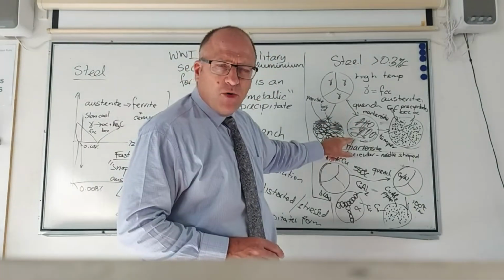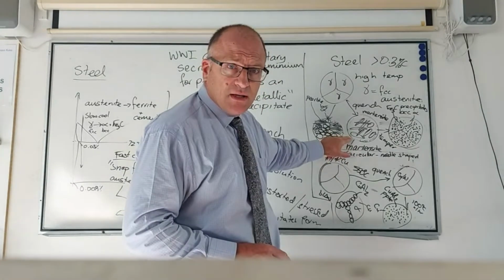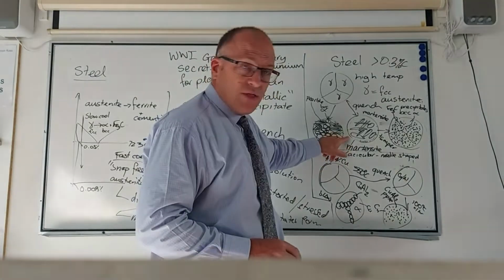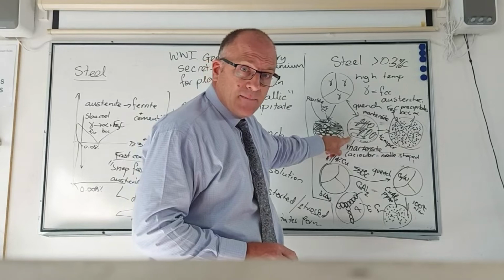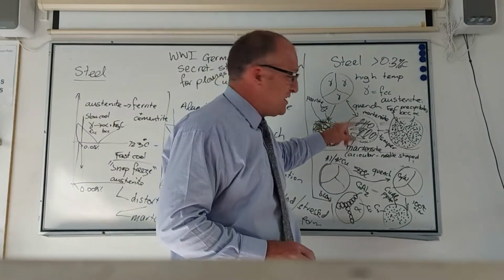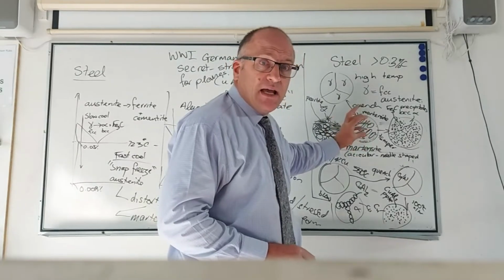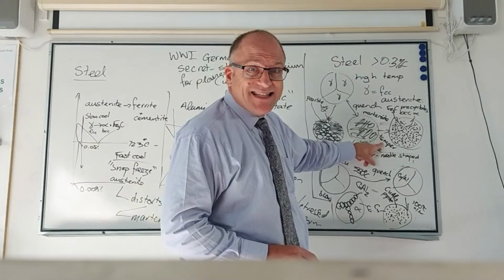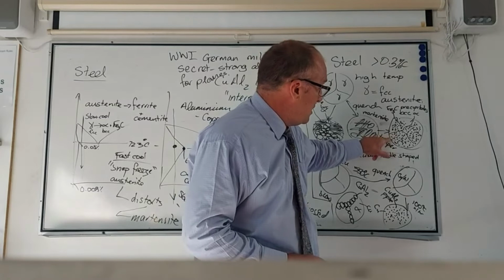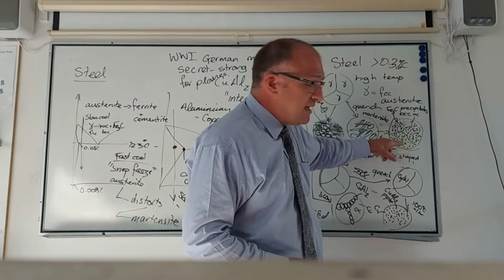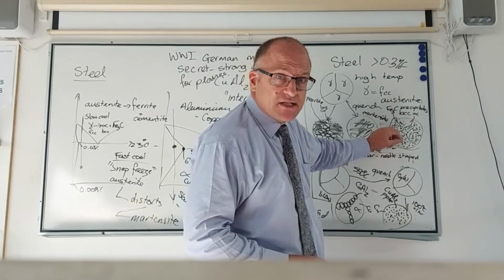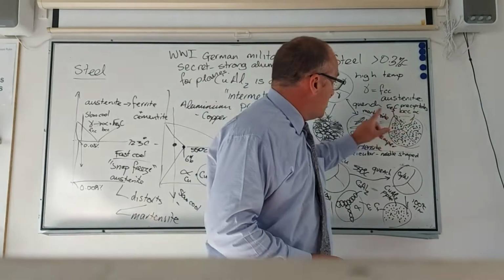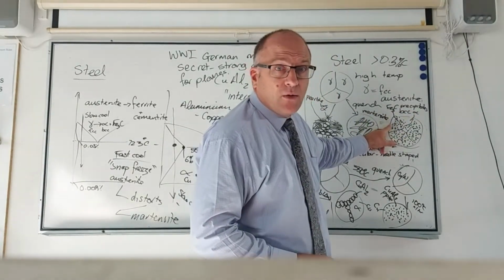This is one particular form of martensite, which the textbooks in the New South Wales HSC syllabus use. It's acicular, it's needle-shaped. Just draw that if you're asked to draw the structure of martensite. It's body-centred tetragonal. It's snap-frozen in a phase it does not want to live in. If you give it a bit of heat, 400 degrees times 10 seconds, 200 degrees times 1 hour, it precipitates out as a fine network of iron carbide, Fe3C, in a lattice of ferrite. That's precipitation hardening of steel.